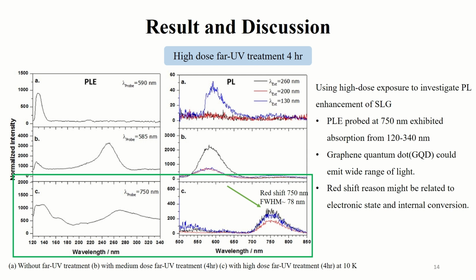In Part C, use high-dose exposure to investigate the PL enhancement of single-layer graphene. So PLE probe at 750 nanometer. The absorption range from 120 and 340 nanometer. This might be because graphene quantum dot could emit wide range of light, so PLE of C part is wide range, and the PL of C part is redshift to 750 nanometer. Its FWHM is about 78 nanometer. This is complementary to PLE spectra, and this might relate to electronic state and internal conversion of electron.